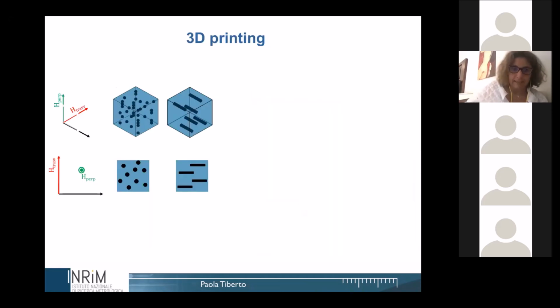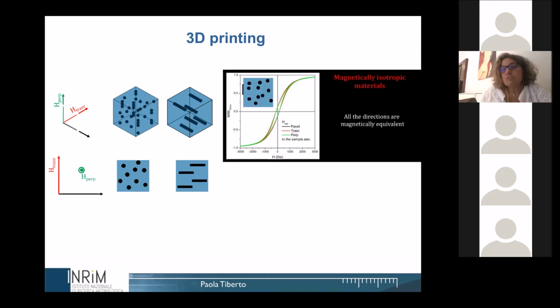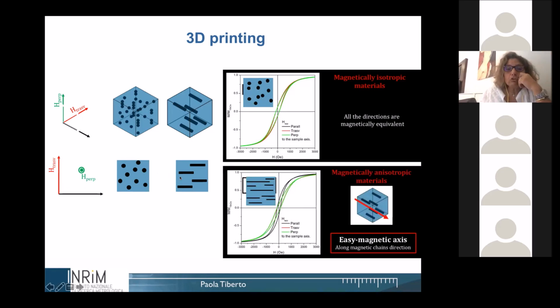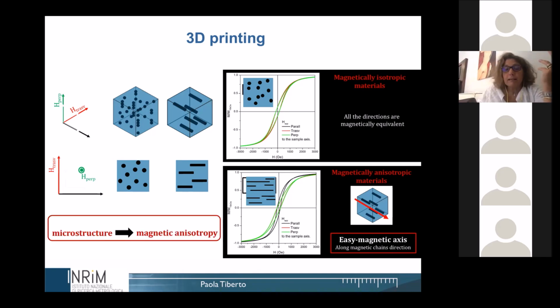What is crucial from the magnetic point of view? Everything, because it depends on the homogeneity of the dispersion, and on the fact that you can apply the magnetic field and create chains inside your matrix. If you deal with homogeneously dispersed particles, your material turns out to be magnetically isotropic, and all three directions shown here are magnetically equivalent because they lead to the same hysteresis behavior. While if you deal with chains, you have a magnetically anisotropic material, and the samples can be easily magnetized along the magnetic chain direction.